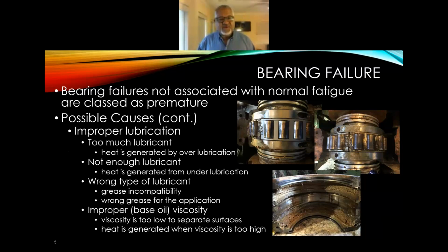Here's more lubricant application causes for bearing failures that will cause premature wear. Improper lubrication. Okay, that sums it up. Well, what is improper lubrication? You use too much lubricant. If you add too much lubricant, you generate heat. Heat of the lubricant degrades the lubricant and can create acids and degrades the bearing. Not enough lubricant, guess what? Heat is generated from under lubrication, but the heat is generated from actual metal-to-metal contact, generating more wear. We could use the wrong type of lubricant.